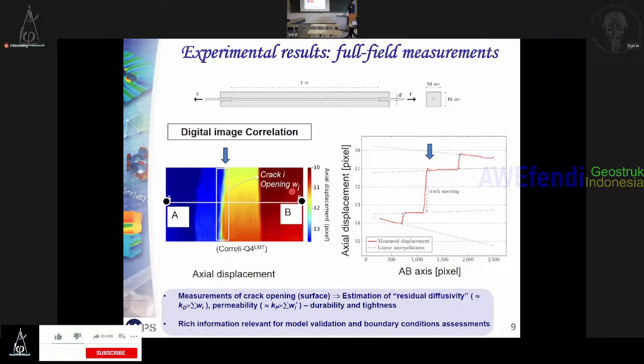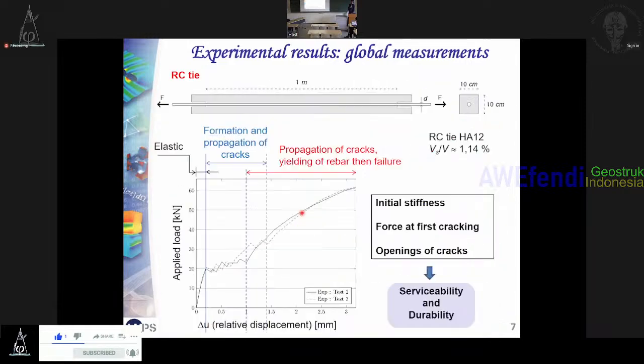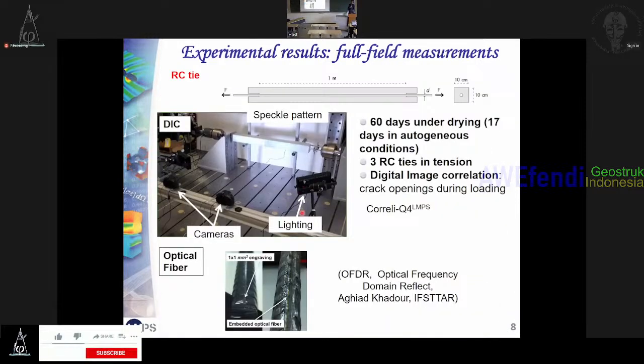This cracking has been obtained by digital image correlation. I don't know if you are familiar with these techniques, but the idea is very simple, though it is not easy to develop this type of software. My colleagues have been working on it for more than 10 years. You have a speckled pattern on the surface, painted with white and blue, and you try to observe the movement of this pattern at the surface of the specimen. You do not look at the displacement of each pixel, but of a group of pixels.